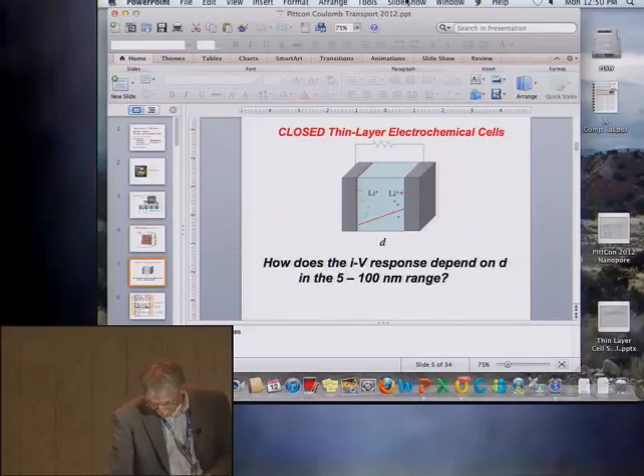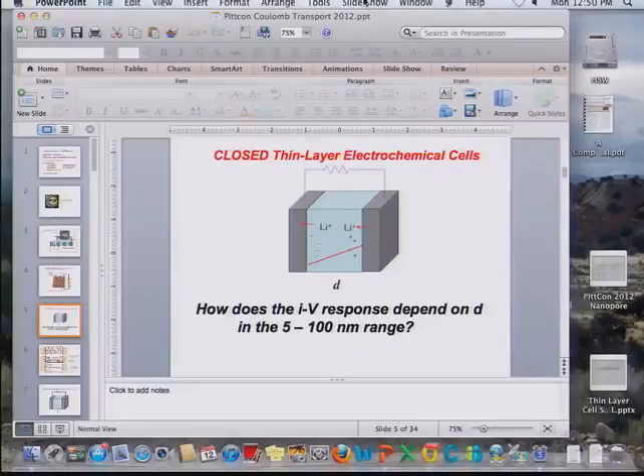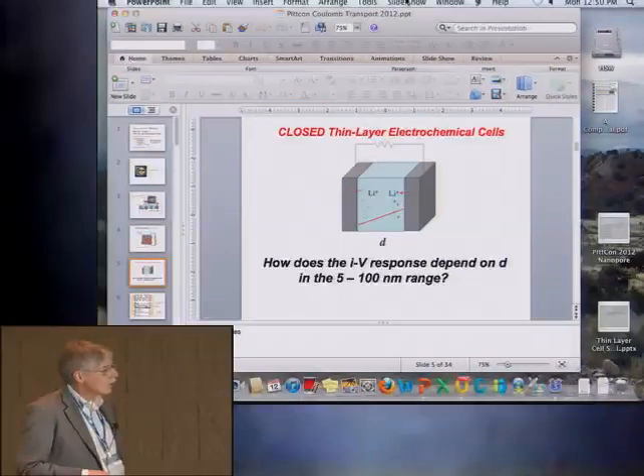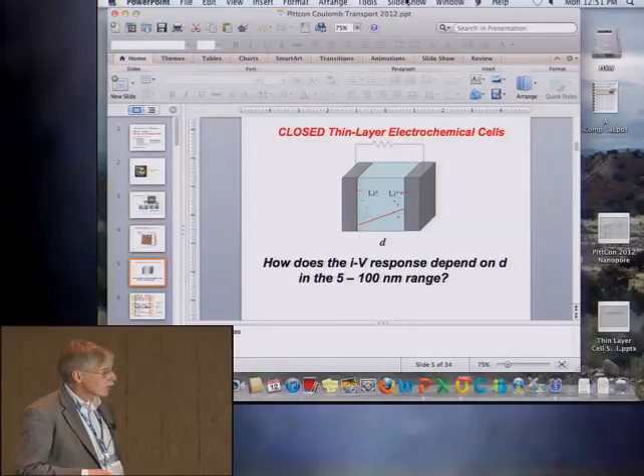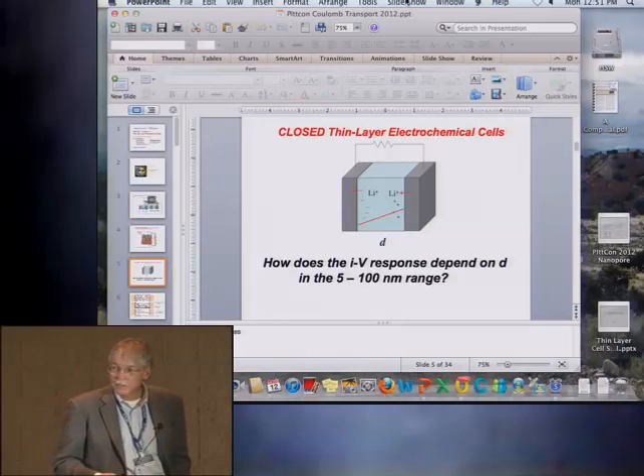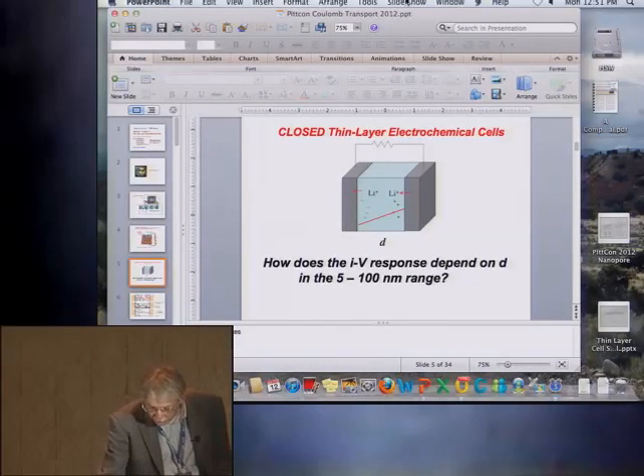And so we started a calculation. This has been a good 15 years ago, of modeling a closed thin layer electrochemical cell. And it's closed in the sense that ions can't get in and out. You start with so many ions, and that's what you live with as you charge or discharge the cell, because that's how a battery really works. It's not an open system. And then the goal is to compute or to understand the current voltage response of such a device as you make the electrolyte thinner and thinner and thinner, getting down into the nanometer range.